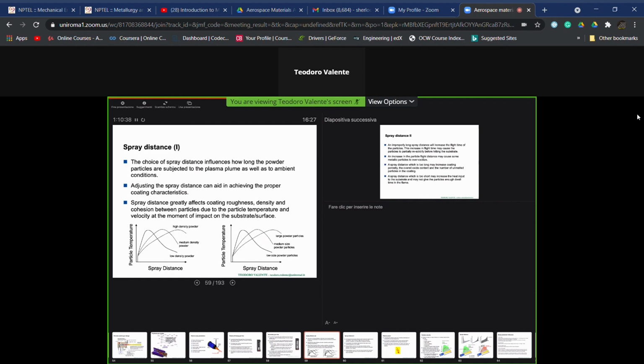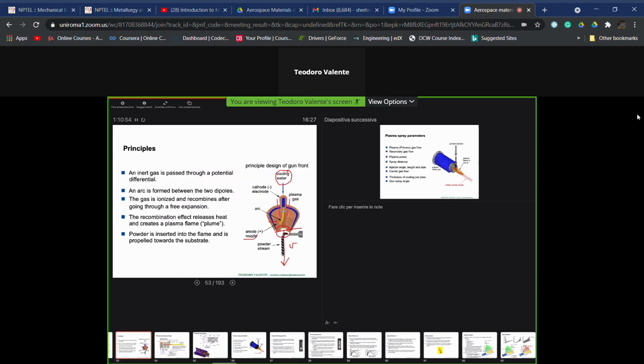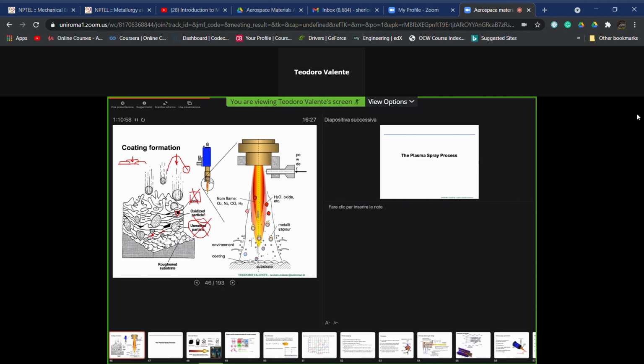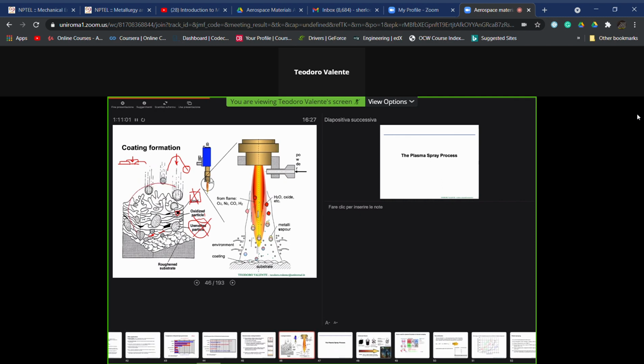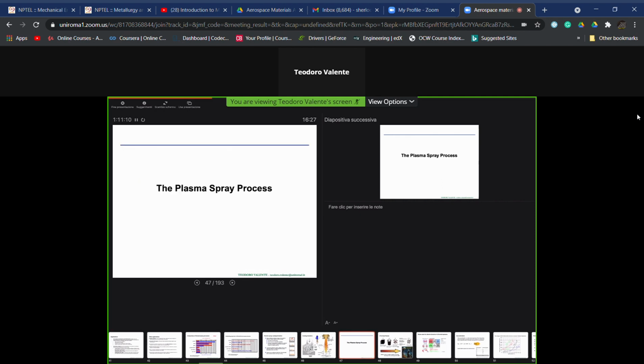we make some trials. We make very flat specimens, which then will be observed under optical microscopy or scanning electron microscopy, depending on the resolution that we want, in order to put in evidence the microstructure, and to understand if that kind of combination is suitable for us in terms of residual porosity, in terms of presence of melted particles, and the same applies also.